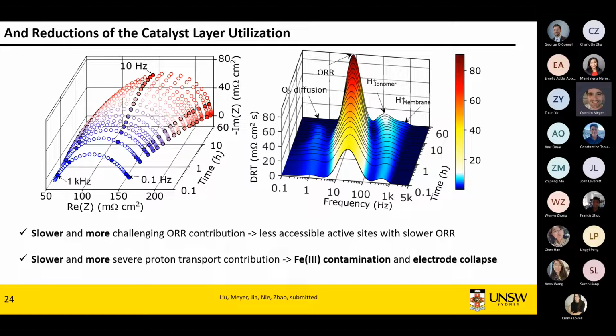So they would be the first ones, the first active sites here. And then as you degrade the electrode, you end up with the second type of active site that is much less active but thermodynamically stable. The other possible approach is that you are still dealing with the same active site, but one is on the surface of the electrode, so very easy to reach. The other one, you've lost the actual surface, and you're only looking at what's inside the volume of your electrode, going deeper and deeper into nanopores. And that would also reduce your ORR.